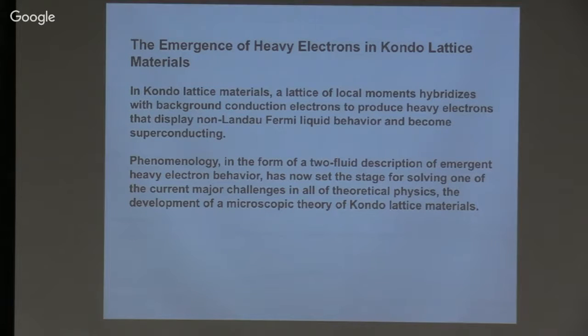Phenomenologically, we're able to sort out what is the underlying behavior of these Kondo lattice materials. And I remind you that the mass of the electrons can easily exceed the mass of the mu meson. They can be between 2 and 500 times the bare electron mass. And these are the objects that can superconduct at quite high temperatures compared to their Fermi energy, which of course is vastly lowered by the heavy mass. Why do they have such a large mass? Because the electron that moves is entangled really with the local spins. It remembers it came from the local spins, and its mass can grow dramatically depending on the coupling between the nearest neighbor local moments.